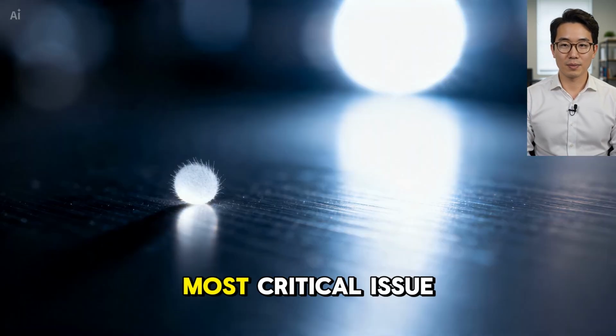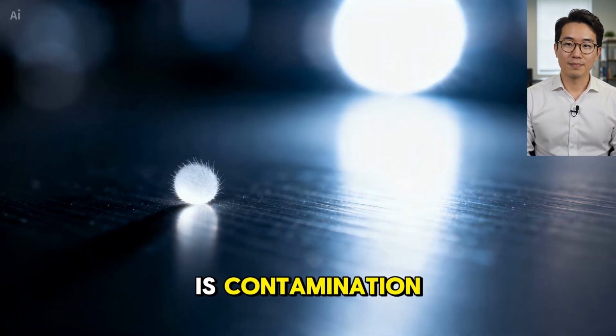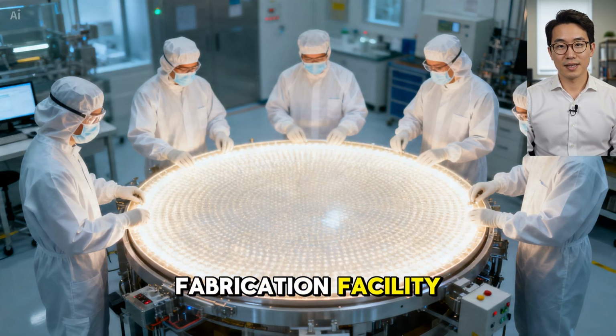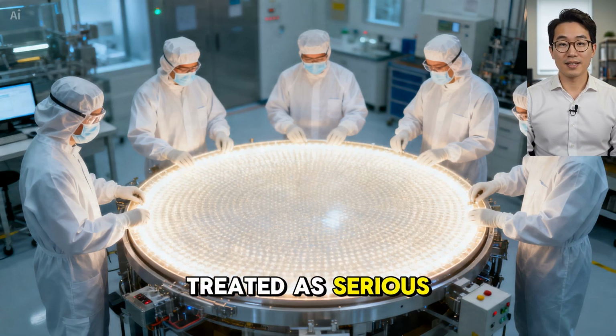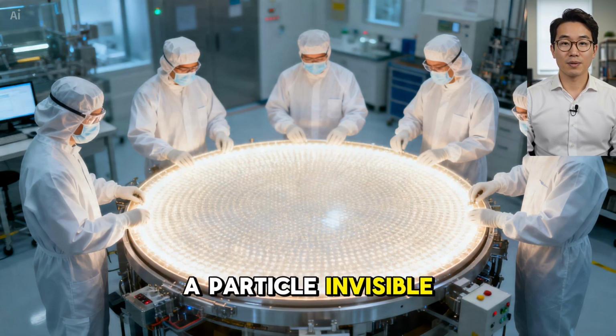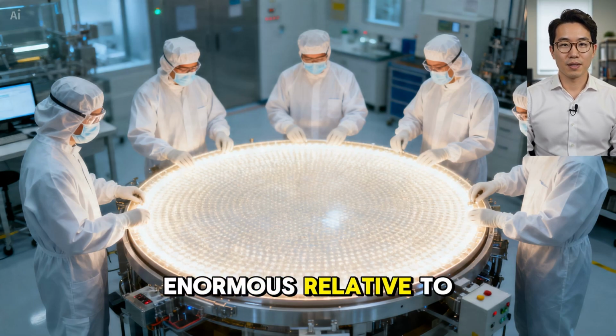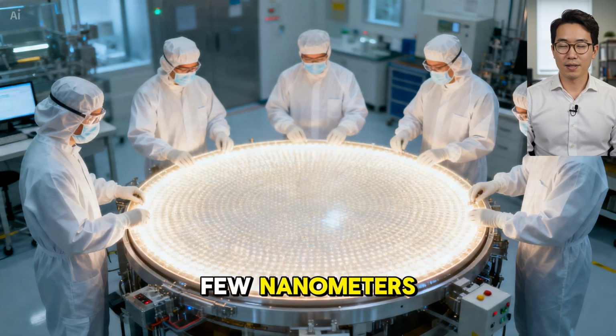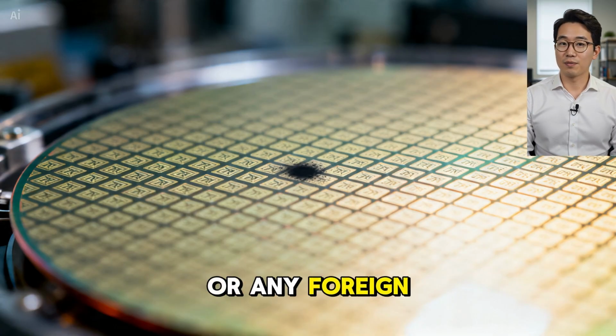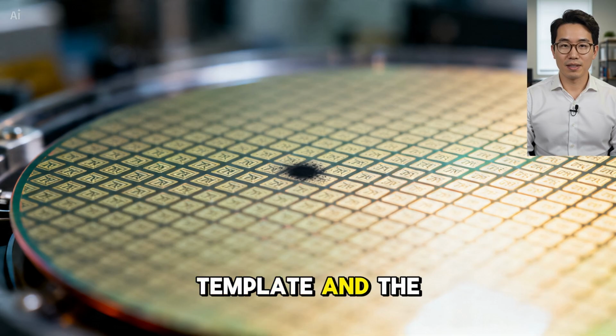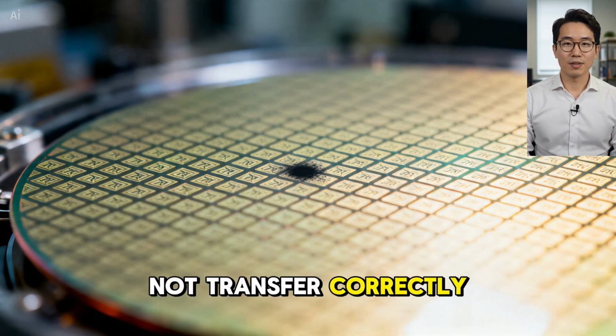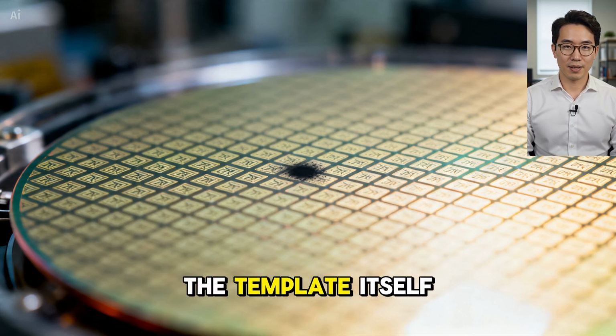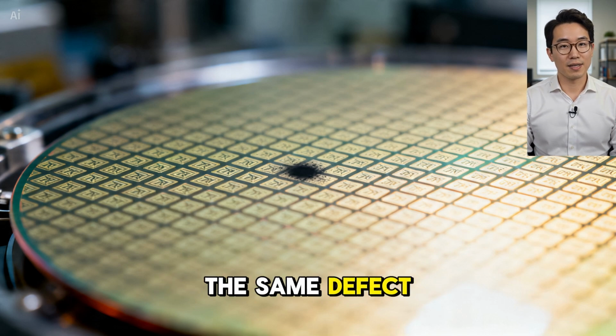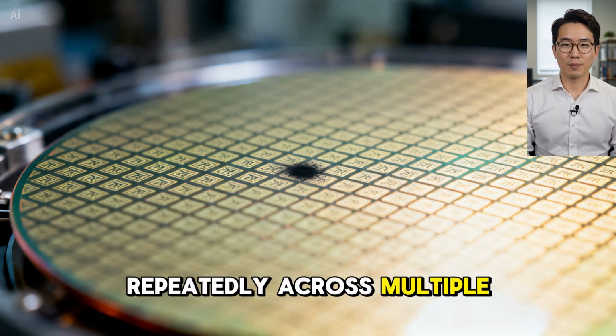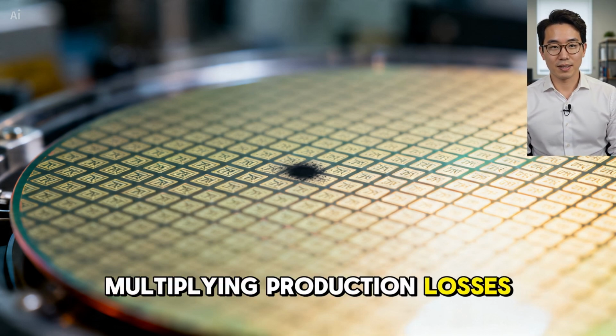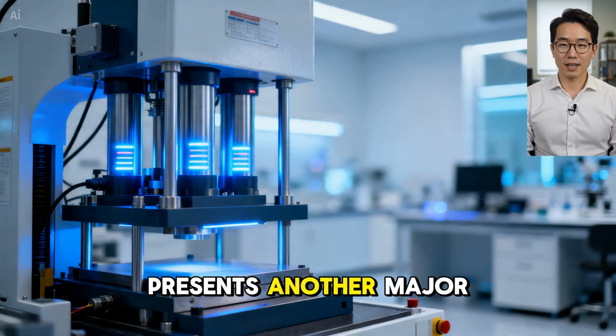The first and perhaps most critical issue is contamination. Inside a semiconductor fabrication facility, even microscopic particles are treated as serious threats. A particle invisible to the human eye can become enormous relative to structures measured in just a few nanometers. If dust, residue, or any foreign material becomes trapped between the template and the wafer, the pattern may not transfer correctly. Worse still, if the template itself becomes contaminated, the same defect can be reproduced repeatedly across multiple wafers, multiplying production losses.